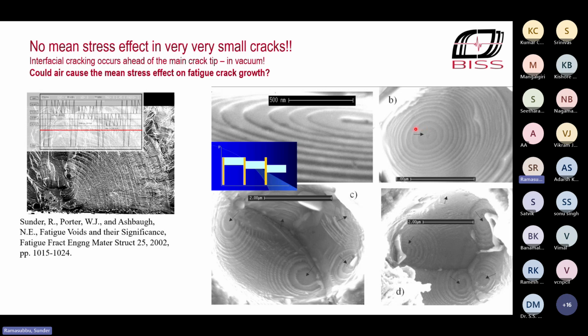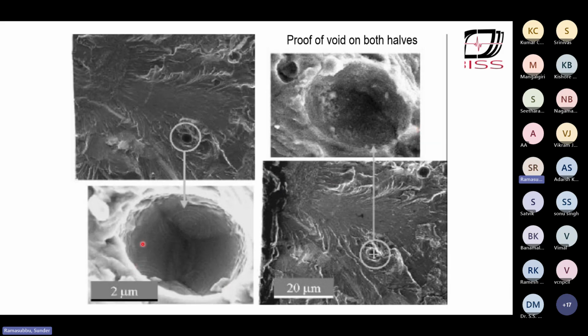I spoke to my colleague there, John Porter. I consider him a wizard in terms of being a microscopist. And I asked him, hey, John, can you just confirm that we are looking at what really happened and not some kind of an artifact? And within minutes, he pulled up the same cavity on the opposite fracture surface. So here you can see the mirror image, but rotated, reversed so that you can compare easily. And you can see that both fracture surfaces, we are looking at exactly the same spot. And there's the particulate that came off. So we were looking at something real. And the possibility that it was really vacuum that played the trick.